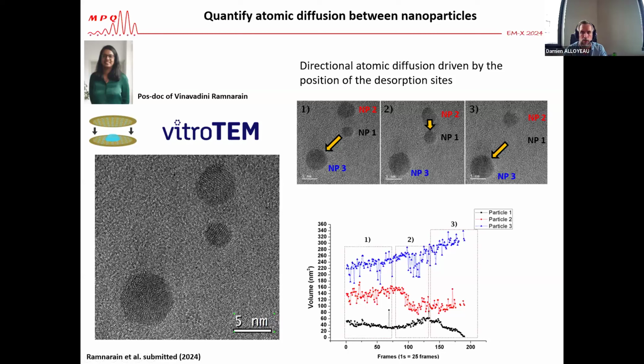So if you want to understand the Ostwald ripening process and which particles will disappear, you should not take into account the intrinsic structural stability of a given nanoparticle, but rather the atomic flux between all the nanoparticles. So it also depends on their environment.